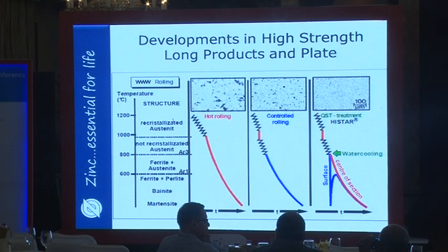What we see with the development of steel is that we are moving from steels where the source of the strength is alloying to steels where the source of the strength is the heat treatments or the transformations. So this is allowing cheaper, leaner steels to be used. In the past years, we've depended upon the alloying additions like molybdenum and chromium and other more expensive elements to provide the strengthening to steels, and these were cooled at slower rates. The availability now of faster cooling was mentioned in Mr. Venugopalan's talk, the first thing about the rapid cooling rates, and this is also true for galvanized structural steels.